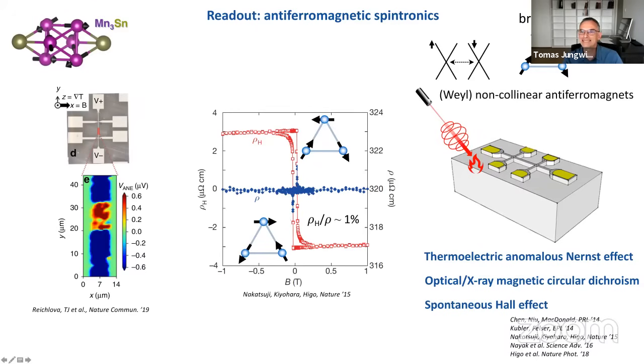In these broken PT symmetry systems, you cannot have the Dirac points, but the Dirac points could split into two doubly degenerate crossings, which are called the Weyl points. And again, if you manage to have these Weyl points close to the Fermi level and no other trivial bands, this can have some singular effects on the corresponding magnetotransport. Again, unfortunately, this doesn't seem to be the case of manganese tin. It is a Weyl antiferromagnet. It does have these crossings, but they're not the only ones that contribute to the anomalous Hall effect. There are also trivial bands that contribute.